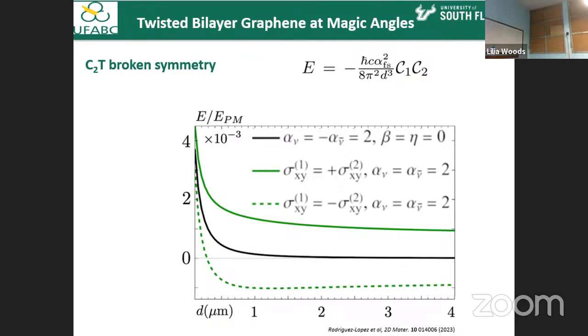graphene, bilayer graphene. And we covered specifically that the interaction now is proportional to the fine structure constant squared times the product of the two Chern numbers. So if the two Chern numbers are both positive or both negative, the interaction is attractive, as you can see here. And when the C2T symmetry is broken, then we don't get that effect.